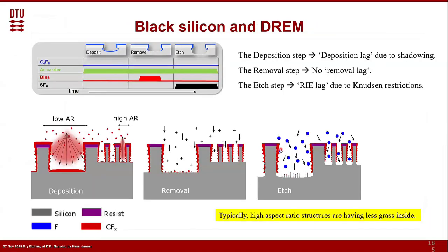Why is that? Well, let's go first for the fluorocarbon process. So what we did was deposit a layer, then we remove it at the bottom with the sharp ion distribution, and then we etch it again with the fluorochemistry. But because the deposition is coming out of the plasma zone, like the etching, where we had RIE lag, where it's going down in structures, the smaller structures are etching slower. Also, the deposition is doing the same. So the big open structures, like low aspect ratio structures, will get more fluorocarbon on the bottom than the smaller ones due to, let's say, the Knudsen limitation. That means if we then go to the removal step, there's much less, and the ions have no removal lag at all because they're all going straight. They don't bother about the wall at all.